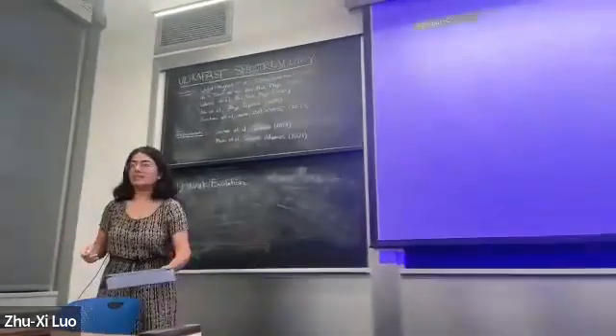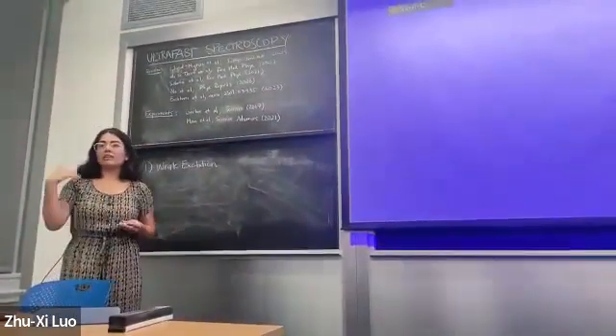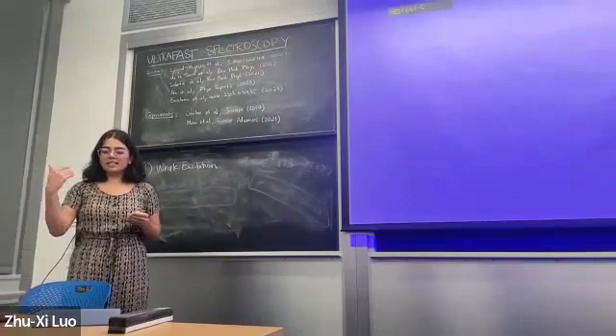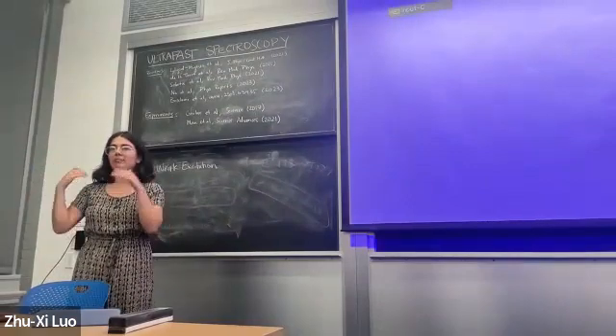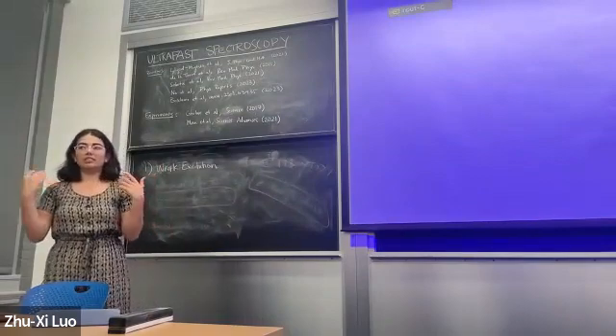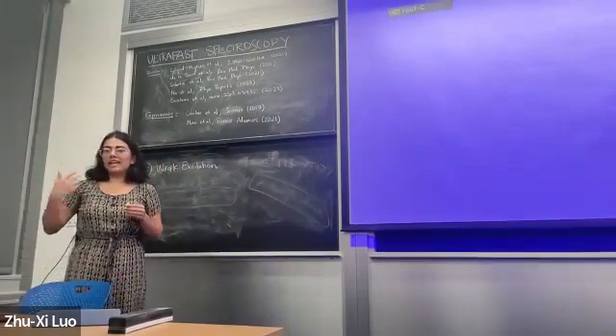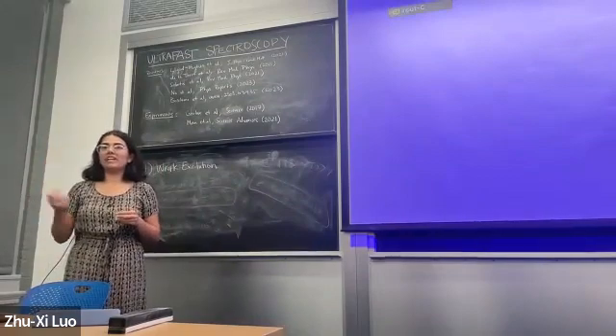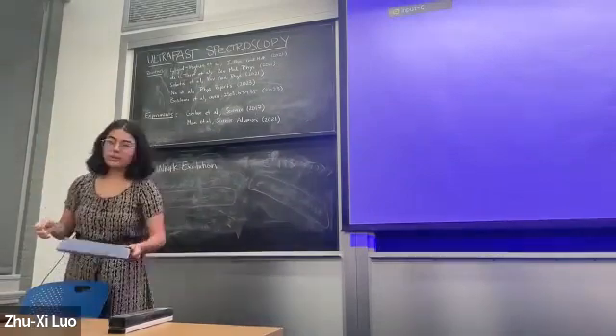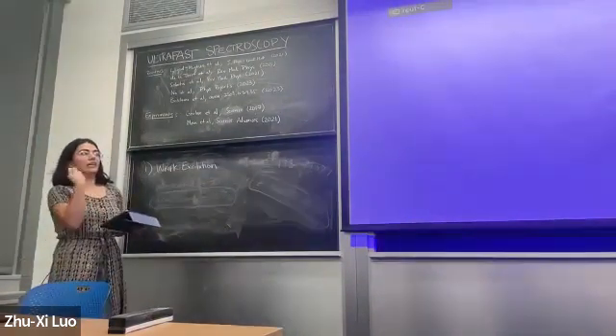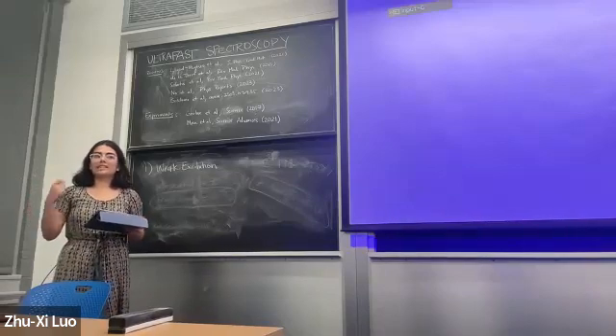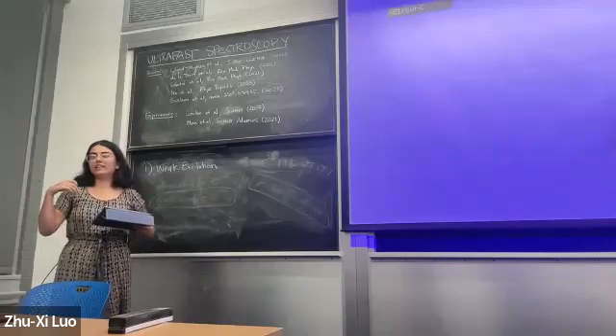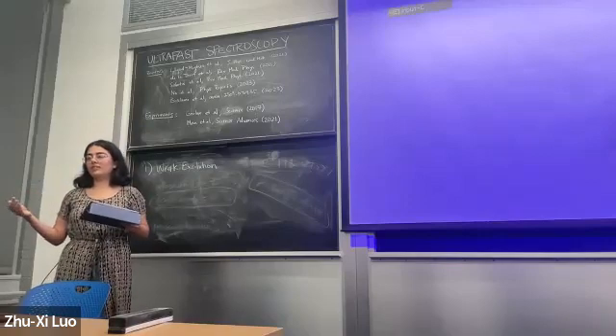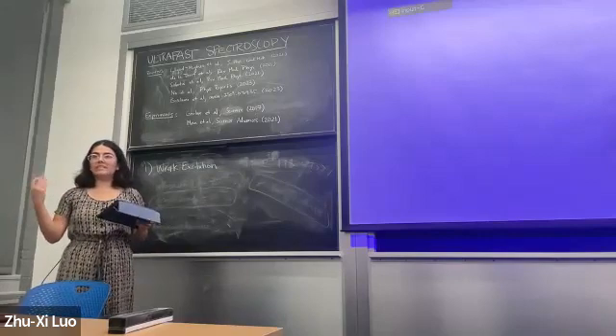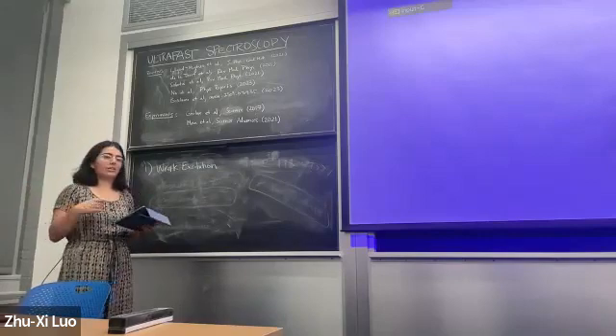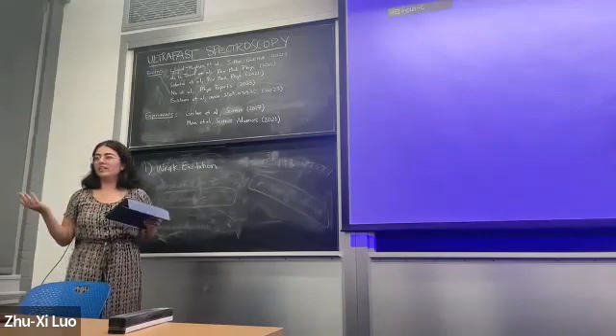regime. In this scenario, the pump pulse that we initially send in to excite our material doesn't fundamentally change the energy landscape or the couplings in your system. You can think it's just maybe exciting some quasi-particles to some previously unoccupied states. And then we want to use our pump probe experiment to see what these excitations are and see their relaxation dynamics back to the original equilibrium, to gain some insight into both the original equilibrium state and also the quasi-particles in our material.